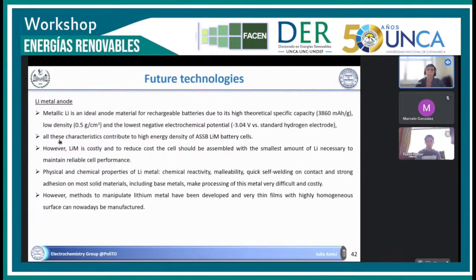Lithium metal anode allows for a really high theoretical capacity, so this is the theoretical capacity, while having a low density. So it should allow to reach high energy density all solid-state batteries. The problem is the reactivity of lithium, which forms dendrites, which can perforate the separator or the solid electrolyte and create short circuits inside the cell. So that's why solid electrolytes are really interesting, because they are supposed to be a barrier against the lithium dendrites.